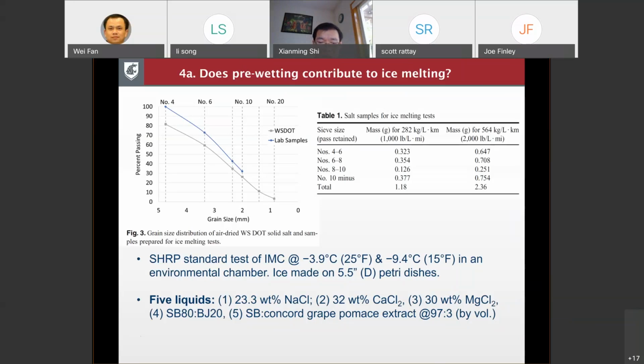Then we basically look at two scenarios, 25 degrees Fahrenheit or 15 degrees Fahrenheit on pavement. Those are not too extreme winter weathers, so these are typical pavement temperatures we're seeing in the field. And then we're looking at 5 different liquids, the typical 3: sodium chloride, the salt brine, and then calcium chloride, magnesium chloride. And then the beet juice blend at 20/80 volume ratio.